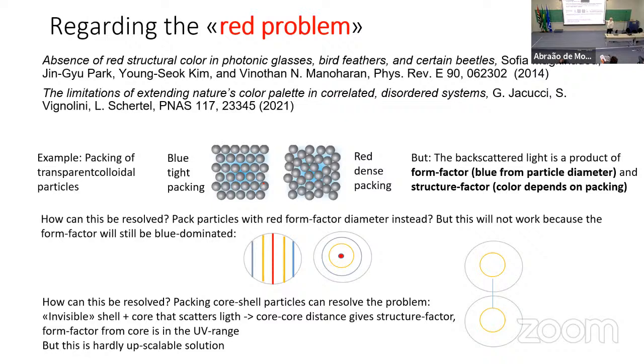But they still have the blue form factor, and that will dominate and destroy the red. That's basically why it's so difficult to make red from structural coloration in this way. You can say, why don't you then make red diameter particles and pack red particles? But if you look at a red diameter particle, it has more blue distances in it than red distances. Say that this is the diameter, but if you move away from the diameter, you get all the other color distances. And the outermost one is blue, and you get mostly blue. So this doesn't help you either. You have mostly blue from a red diameter colloidal particle.